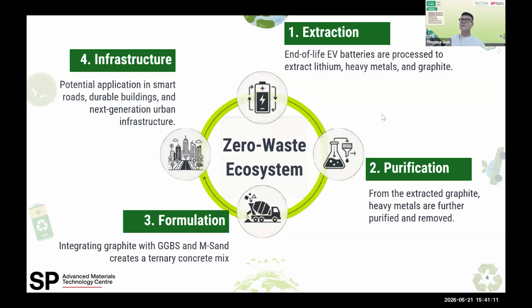So usually the graphite carbon and the heavy metals will come together as what we call black mass. Then from there, you go through further purification, which is step number 2, which tries to separate the metals from the respective compounds. The reason is that battery manufacturers want to sell the material back to the raw material suppliers. So they want to separate the lithium to sell as lithium, or sell the iron, the nickel, the cobalt, and not forgetting the graphite. Graphite for them is probably the least important because of its lower value compared to the other metals.